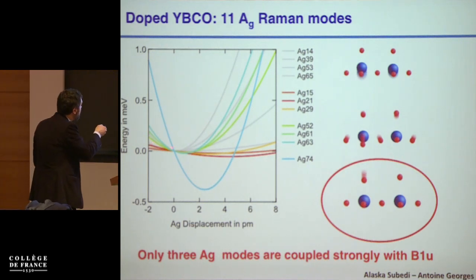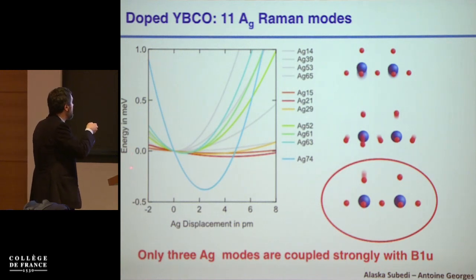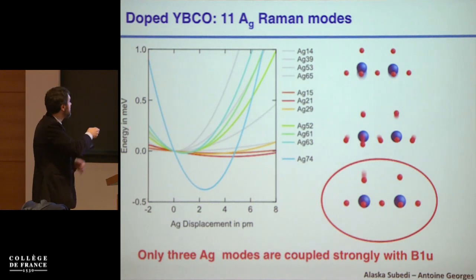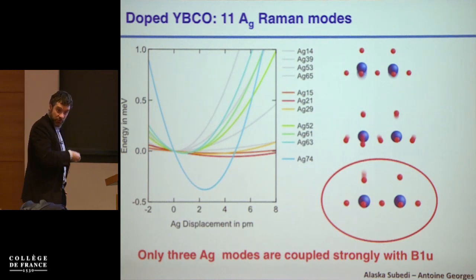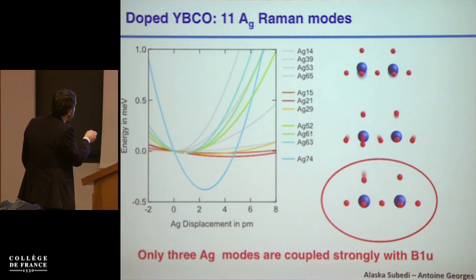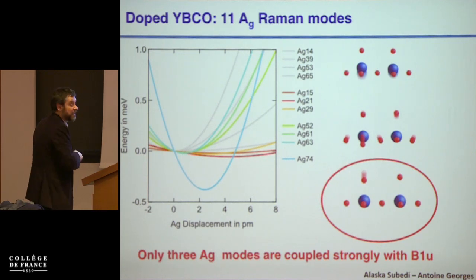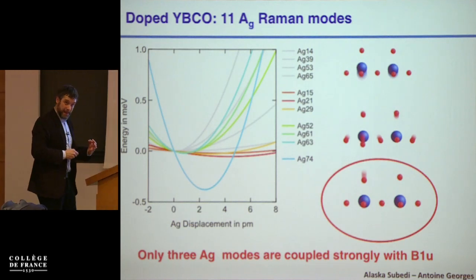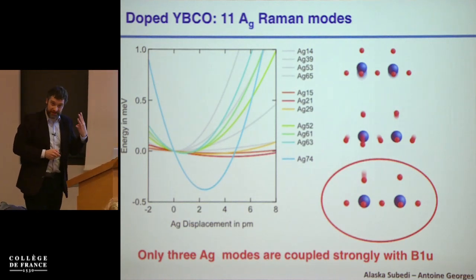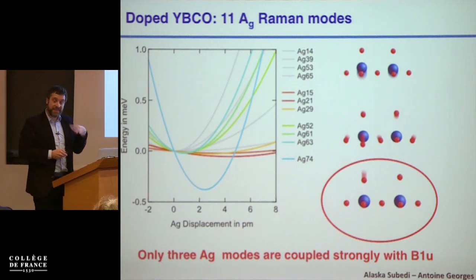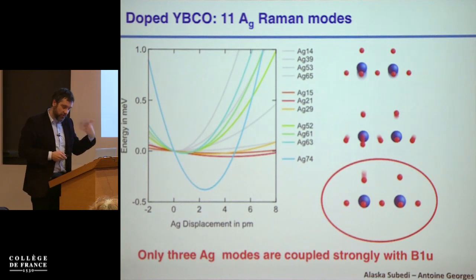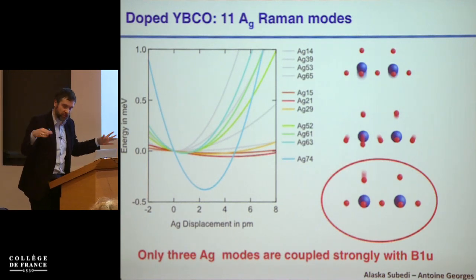But the ones that are strong tell you, when you excite the B1U apical oxygen distortion by a frozen phonon, by a frozen amount, how much the equilibrium position of each one of these other A modes shifts due to this Q square Q coupling. You can see that in some cases the shift is small, but in case of these guys, which are rather sloppy potentials, the shift can be very large. So we identify three modes that are important to this order, and then we also identify higher order contributions that I will not tell you about, but we've done measurements where we could exclude that other contributions like the Q square coupling would be important.